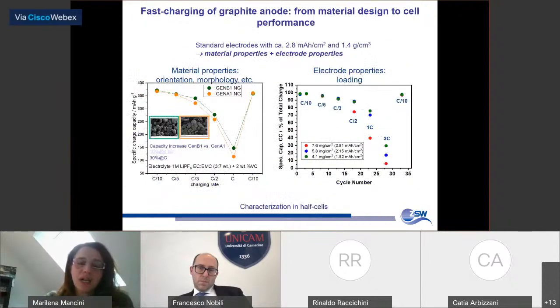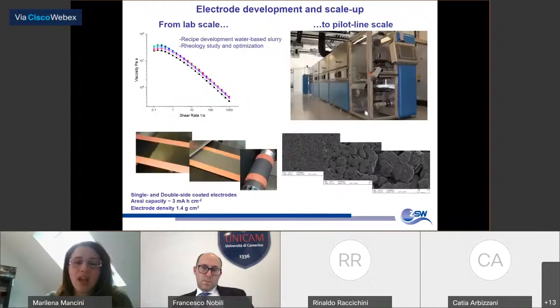As I said before, at the electrode level, when we speak about practical application, we have to go to electrodes which have higher loadings and densities. And also in this case, while taking into account the effect of the parameters at electrode level, we can still observe a difference between these two materials. So that means even though the morphology looks very similar, the different materials offer completely different performance at the electrode level. It is very important also to check the processability of the materials.